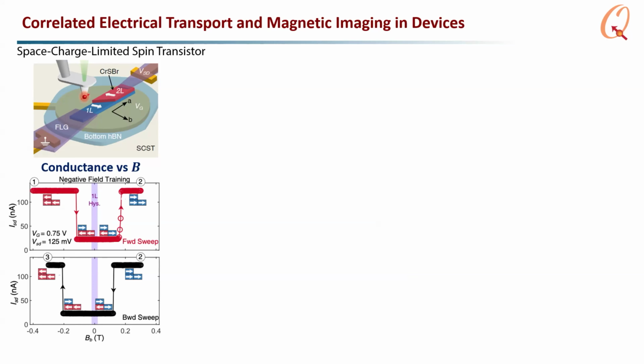So this is a new device we made called a space charge limited spin transistor, where you have to conduct electrons across the 2D magnet, where one of these contacts touches the top of the 2-layer and one touches the bottom of the 1-layer. Okay, so they're made to opposite sides of a monolayer-bilayer junction, and then you have to conduct through the 2D magnet rather than tunnel across.